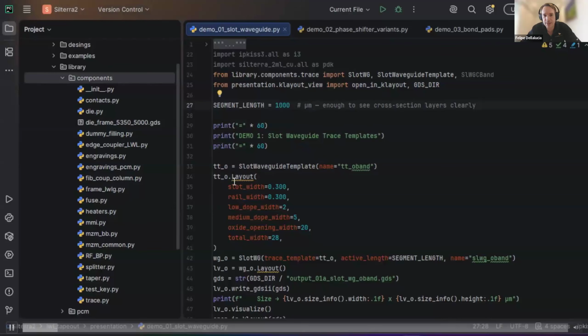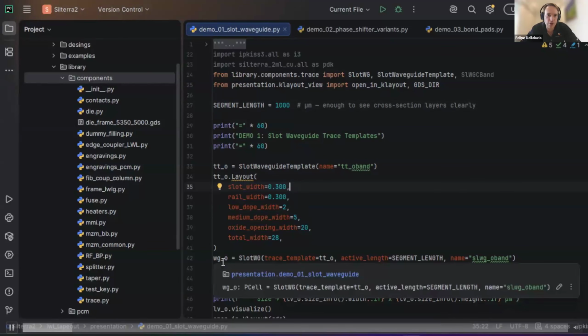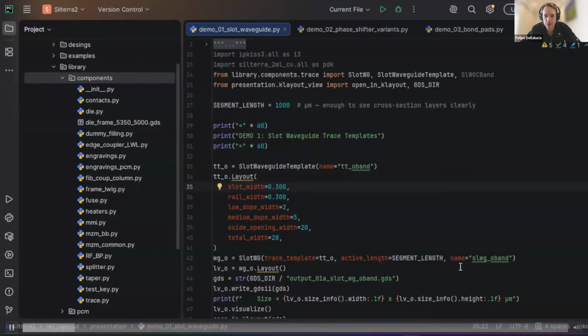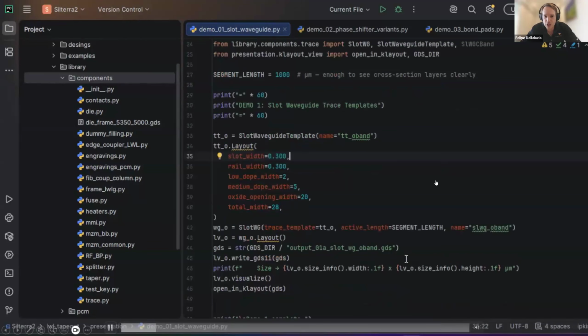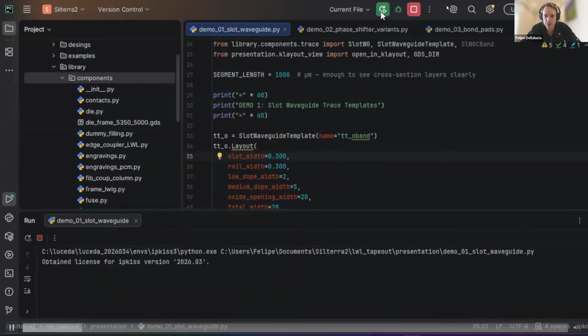We set the segment length of this waveguide, for instance, 1 millimeter, and we can set some parameters of this waveguide, such as the slot width, the rail width, the doping profile, and the oxide open window that you're going to have in your slot waveguide. And then you just instantiate the component like shown below.